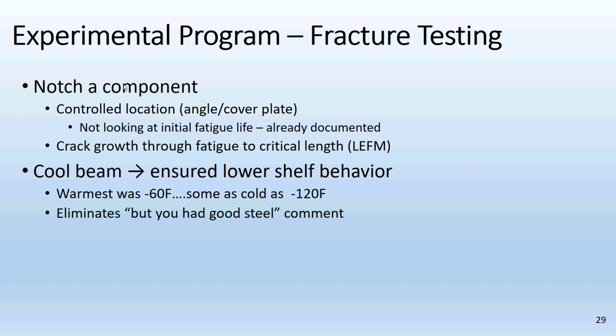And if you think about what's happening, as we learned as we studied this, as the component begins to crack, it gets softer, and it begins to shed load to the uncracked components. Now, that behavior is actually really good, because what that means is the load in the member begins to come out of it. But from a fracture point of view, if you want something to break, it's not a plate that's isolated, which is normally how we think of fracture tests.